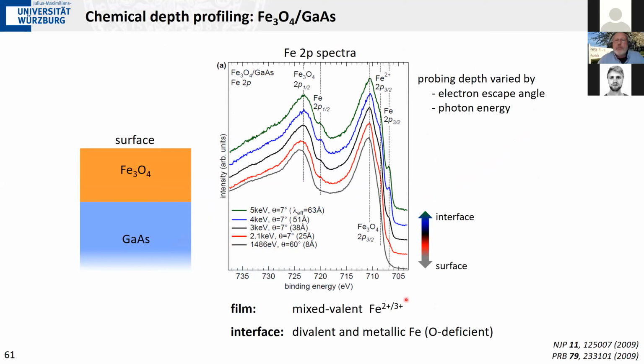And you can see here as we go from surface sensitive to interface sensitive. So here we increase the probing depth from surface sensitive to looking deeper into the magnetite film to see also the interface. You can see characteristic changes in our spectra, which tell us that we have a mixture of different valencies, as you would expect in magnetite, but this mixture changes in relative proportions. At the interface, we see mostly divalent and metallic iron. Divalent because we see this characteristic charge transfer centroid. The green spectrum is the one with the highest interface sensitivity. And here you have a peak that is clearly not from an oxide, from oxidized iron, it's metallic iron.